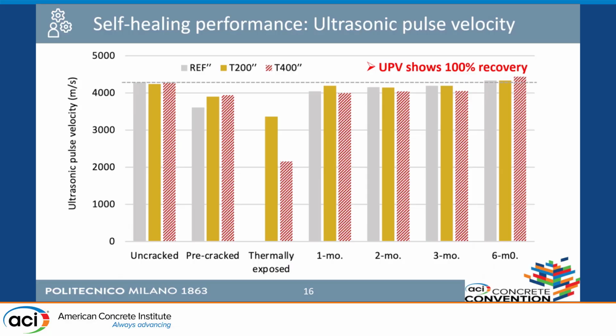Here, let us focus on what happened after 1 month, 2 months, 3 months, and 6 months. You see that we have a recovery of the properties that is quite fast, because after 1 month we already have a good recovery. Pay attention that the elastic modulus is proportional to the ultrasonic velocity to the second power. So these differences should be squared to get an idea of what happened in terms of elastic modulus. We will see later in the summing up slide.